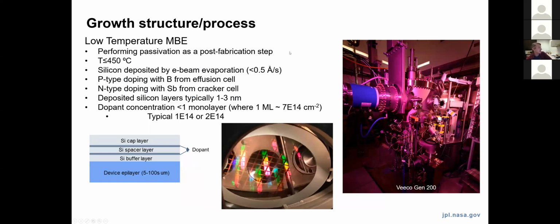So how does this process happen in the microdevices lab? I mentioned molecular beam epitaxy. This is an ultra-high vacuum deposition process. So generally, this passivation is always performed as a post-fabrication step. So we'll take a complete CCD or CMOS wafer, essentially, with completed devices, perform a backside thinning process to get down to the active device thickness that we want, and then perform this MBE process. So this is a low temperature process. We need to maintain a thermal compatibility with the wiring and other stuff that's on the front side.